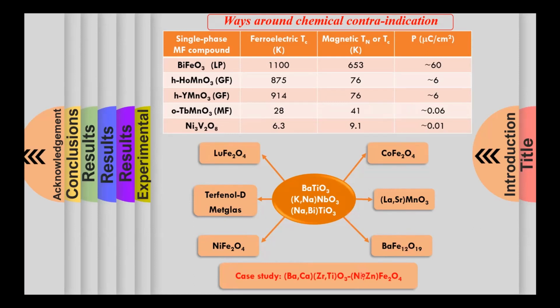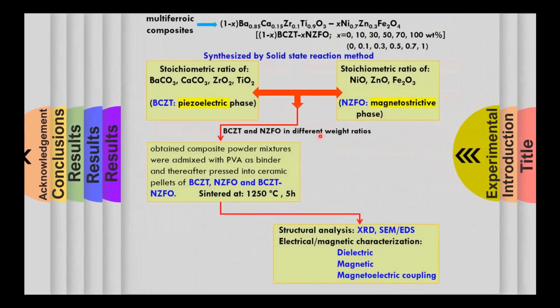But here I will discuss only the specific case of BCZT, which is the modified barium titanate, barium calcium zirconium titanate, and its composite with the magnetic nickel zinc ferrite phase. So the solid state reaction method was utilized for the fabrication of multiferroic composites, BCZT with nickel zinc ferrite, where BCZT is the piezoelectric phase, while the nickel zinc ferrite is the magnetostrictive phase. BCZT was chosen keeping in mind its very high piezoelectric coefficient, which is around 350 to 400 picocoulomb per Newton. And the ferromagnetic nickel zinc ferrite was chosen for its high magnetostriction coefficient.